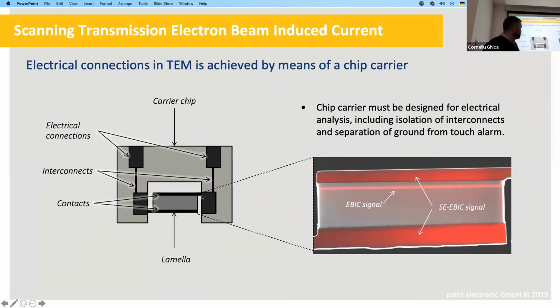The lamella would typically be connected on two sides, left and right, and in our image this would show as top and bottom. Those are then carried through the tracks, through the chip, through the holder, out into the electronics, so we can measure the small currents. So we see we have some signal. Again, this is a HAADF image in gray overlaid with an EBIC image in red. And we see several things in this image. One of them is emitted electrons coming from these thick deposited connections.